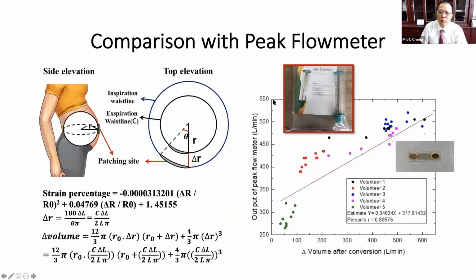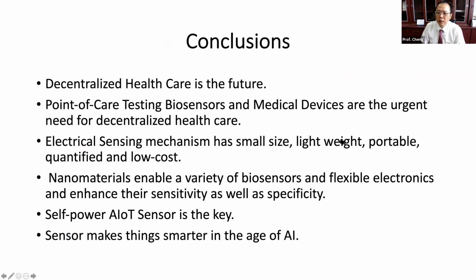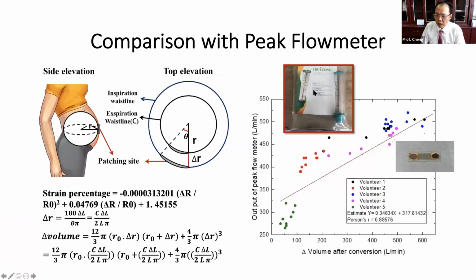And also we try to compare with the commercial measurement instrument. You can see this is the flow meter. We call it a peak flow meter. The students just blow into the peak flow meter, and we also attach the sensor onto the stomach, and we can extract the signal. After we theoretically convert to the flow and the volume, we can have this data. And the Pearson ratio is about 90%. So that means our sensor is really sensitive, and the same as the result.